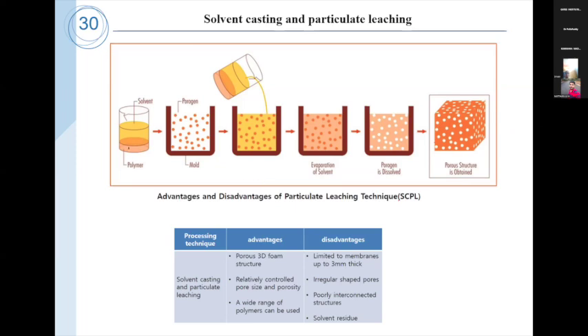particles. Because here we are mixing the polymer solution with porogens like sodium chloride salts. Once we mix, we pour it into a particular mold. Once we evaporate the solvent and keep it in water, the salt particles are leached out, so that porous structures are created within the scaffold. That's why it can provide flexibility in controlling pore size and distribution by adjusting the porogen particles. We can even add different types of porogen particles also.